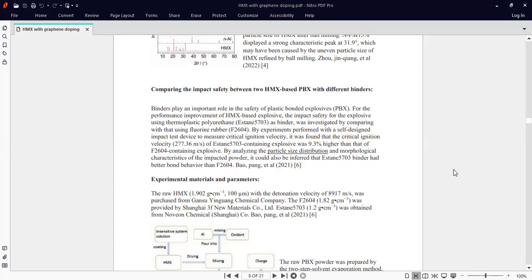by comparing with the use of fluorine rubber, by experiment performed with a self-designed impact test device to measure critical ignition velocity. It was found that the critical ignition velocity, which is 277.36 m/s for Estane 5703 containing explosive, was 9.3% higher than that of F2604 containing explosive. By analyzing the particle size distribution and morphological characteristics of the impacted powder, it could also be inferred that Estane 5703 binder has better bond behavior than F2604.